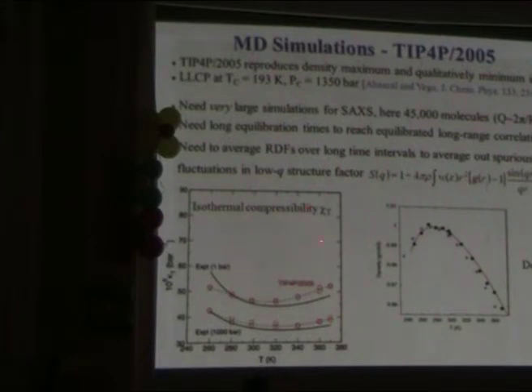We also need a force field that can actually reproduce the isothermal compressibility reasonably well. The TIP4P 2005 model is actually the best model for the thermodynamical properties. So we do these simulations, and here we compare directly with experiments.